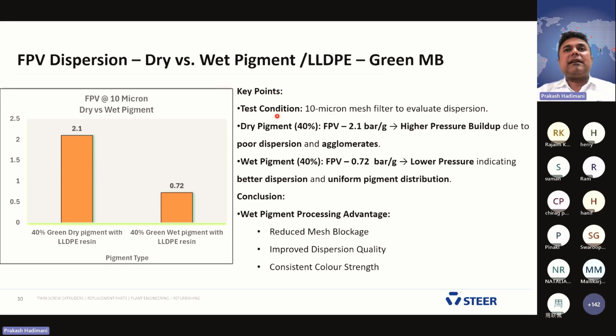What are the key points? Test condition: we used 10 micron and 40% dry pigments, with a filter pressure value of 2.1 bar per gram. What did we observe? Higher pressure buildup on the screen or the filter due to poor dispersion and agglomerates. We can visibly see that. In the wet pigment, we observed a filter pressure value of 0.72 bar per gram, a low pressure indication, better dispersion and uniform pigment dispersion. Finally, the wet pigment process advantages: reduced mesh blocking or filtration blocking, improved dispersion quality and consistent color strength.